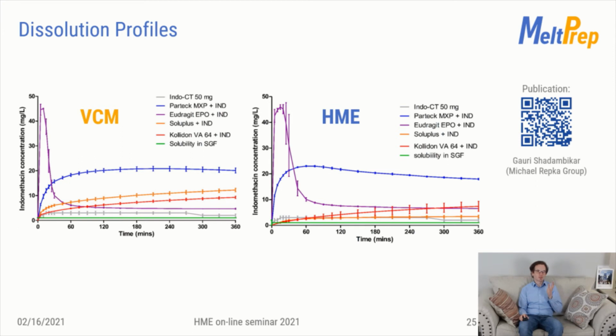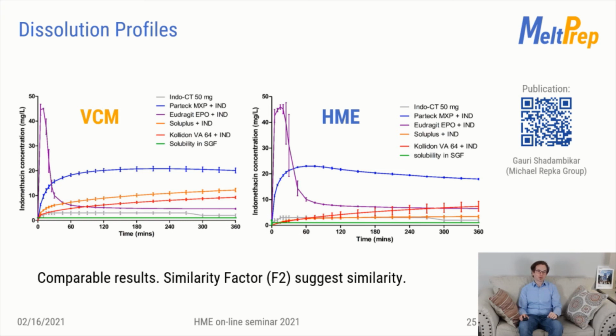What you can see here is a very good agreement between VCM as a screening approach, requiring only 1 gram of material per formulation, and the processing approach, hot melt extrusion. This was also confirmed with the similarity factors. The dissolution data before was generated on milled material, but there is no need to mill them. You can work with the VCM samples directly.